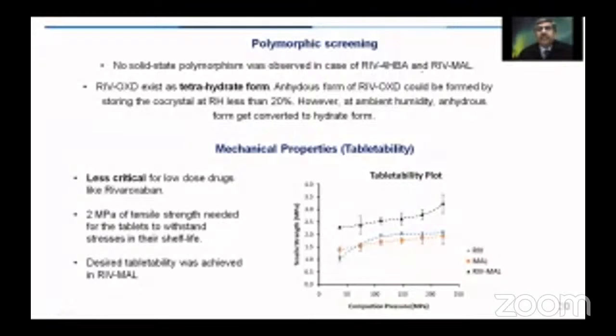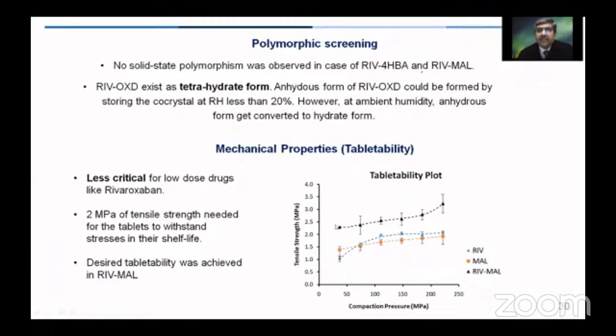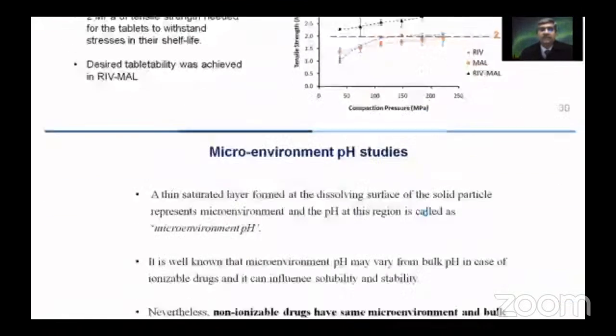The mechanical properties in terms of the tabletability were evaluated. This is a low critical pre-formulation parameter for a low dose drug like rivaroxaban, because the dose that we were working on is only 20 milligrams. Nonetheless, we evaluated their compactability profile, and we found that the co-crystal with malonic acid has a reasonably good tabletability, and it gives us a value which is higher than the 2 megapascal. So this is the tensile strength which is optimally required to form a good quality tablet, and we were getting a value which was higher than this.